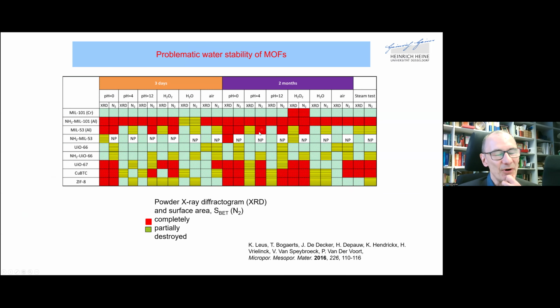Now comes the problematic issue I have to point out. MOFs are not really immediately evident for any use when water plays a role. For a long time, it was neglected that MOFs are rather water sensitive. It's no wonder, because MOFs are nothing else than three-dimensional coordination network compounds. And coordination chemistry is well aware that water is also a great ligand and can replace over time, through its large concentration, the existing ligands in a coordination compound. And the same thing happens in many MOFs. So if MOFs are exposed to water or air, which carries water with it, for 3 days or also for an extended time, 2 months, many MOFs degrade.